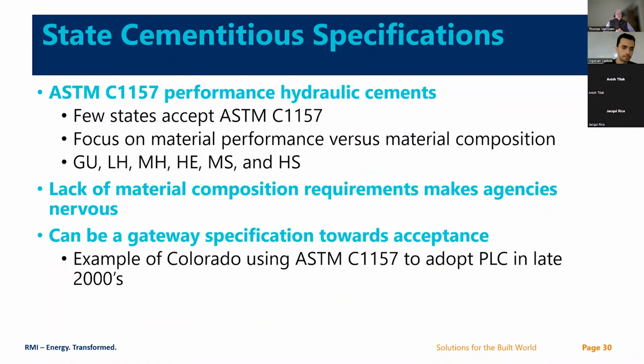Very few states and agencies allow for performance specs for hydraulic cements. These fall under ASTM C1157. There's not an AASHTO equivalent, and they really focus on material performance versus material composition. The lack of material composition definitely makes agencies nervous. And yet some agencies have used ASTM C1157 really as a gateway towards adoption of something like PLC, where the state of Colorado was a leader in adoption in the late 2000s. At that time, PLC was not under the ASTM C595 spec. But even since then, Colorado has gone to pulling back from using ASTM C1157. So that is a potential spec avenue, but not well utilized. Next slide.